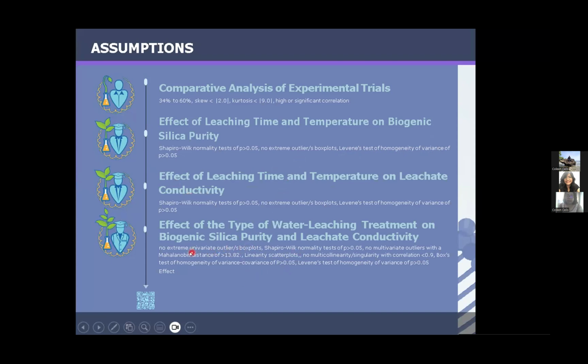Also, for the last portion of my results and discussion, which is the effect of treatment on purity and conductivity, first, the same: there should be no outliers using box plots. I made box plots for all of these. And then the Shapiro-Wilk normality test again. Then multivariate outliers; this is what differs, because we have to calculate the Mahalanobis distance of greater than 13.82, since that is the critical value. And then linearity with scatter plots, so the scatter plot should be linear.